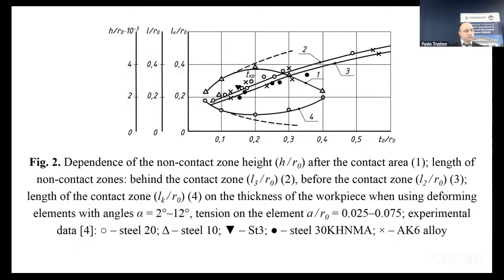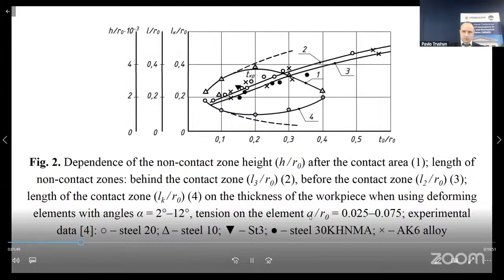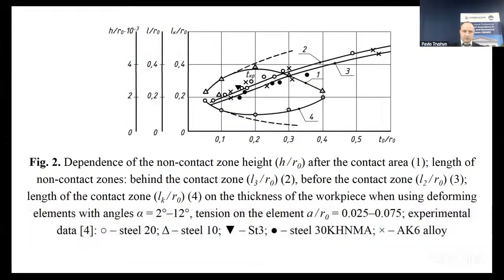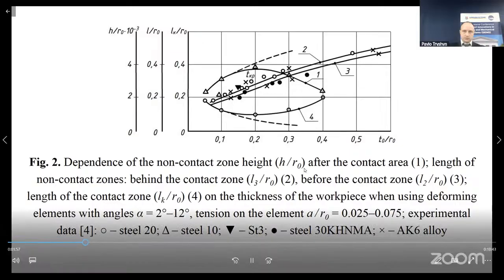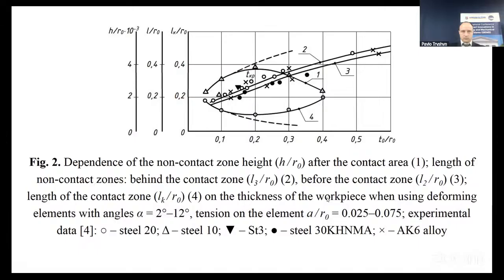As shown by the results of the calculated and experimental data, Figure 2, the axial dimension of the non-contact zone calculated by the model increases monotonically with increasing wall thickness and coincides well with the value of experimental data. At the same time, when determining the contact length and the height outside the contact zone behind the contact area, curves 1, 4, the coincidence of the calculated and experimental result is observed only for the case of machining thin-walled workpiece. Therefore, the results obtained according to the model are valid only for the deformation of thin-walled parts.